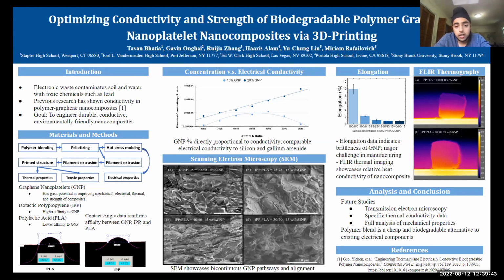We conducted electrical conductivity data, and we could see a maximum on our 15% graphene graph at the 40-60 PP to PLA ratio, and this was about 1 × 10⁻⁵ Siemens per meter. At the 20% graphene sample, our electrical conductivity just kept increasing, and we did see a maximum around 1 × 10⁻⁴ Siemens per meter. We saw that with increasing graphene concentration, there was a significant increase in electrical conductivity, and this was similar for thermal conductivity.